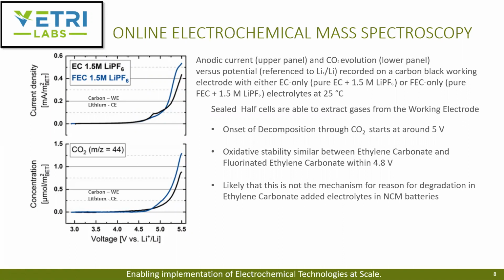From this test, they could see the electrochemical oxidative stability was similar between the ethylene carbonate and fluorinated ethylene carbonate system until at least about 4.8 volts. So this could not be the mechanism for what they were seeing with the ethylene carbonate added electrolyte system, because the fluorinated ethylene carbonate and ethylene carbonate systems decomposed in a similar fashion. They concluded this cannot be the mechanism for what they were seeing with the ethylene carbonate electrolyte system.